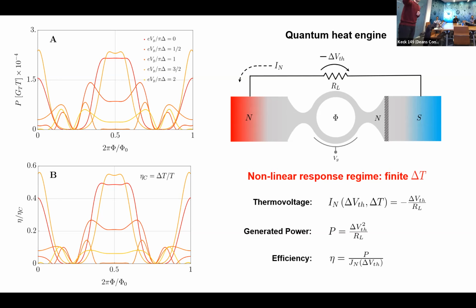And this thermal voltage can be easily obtained by solving numerically this first equation, which corresponds basically to the Kirchhoff law. So the current inside the normal lead just corresponds to the current passing through the load resistance. By solving numerically this equation, you can obtain the thermal voltage, and using it, you can compute, for example, the power dissipated by the system on the external load resistance, which is basically the ratio between delta V squared over R_L. And knowing the power, you can also compute the efficiency of your system, which is just the ratio of the power and the absorbed heat current J_n.